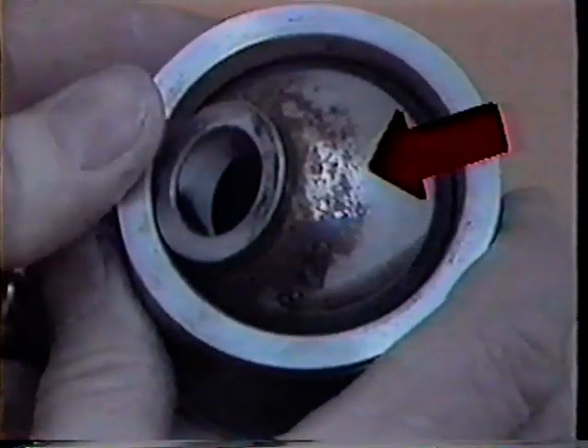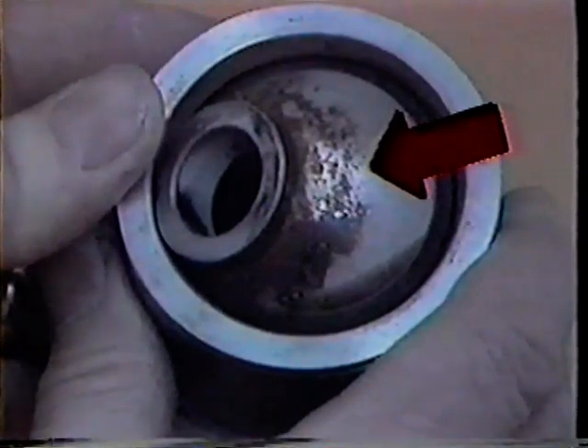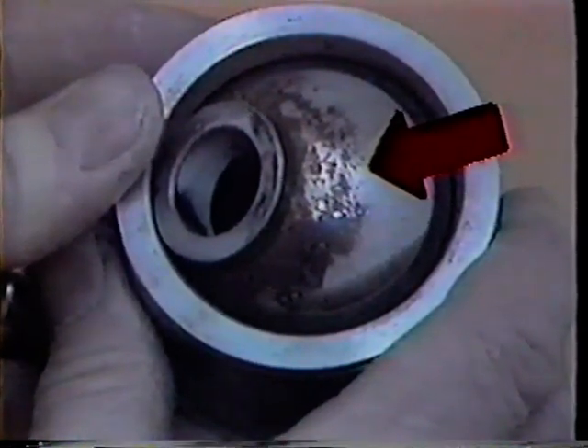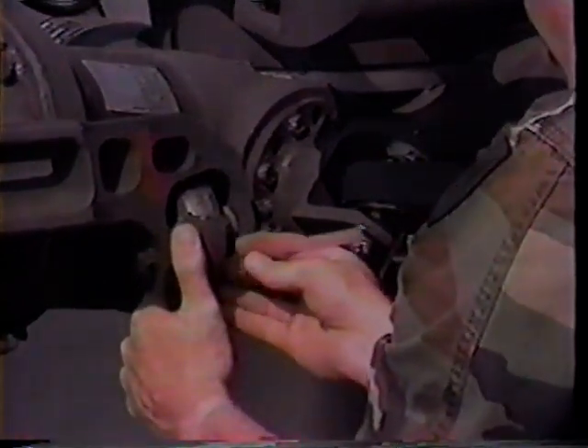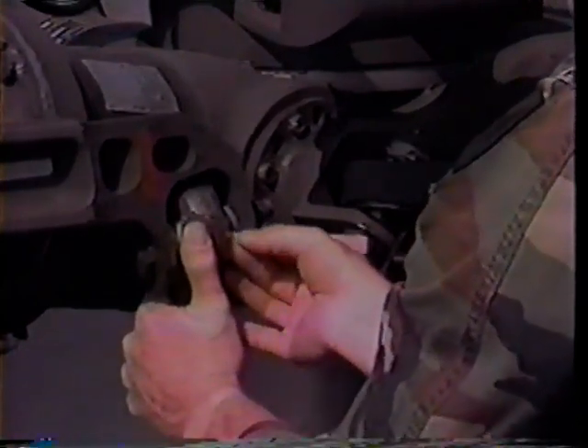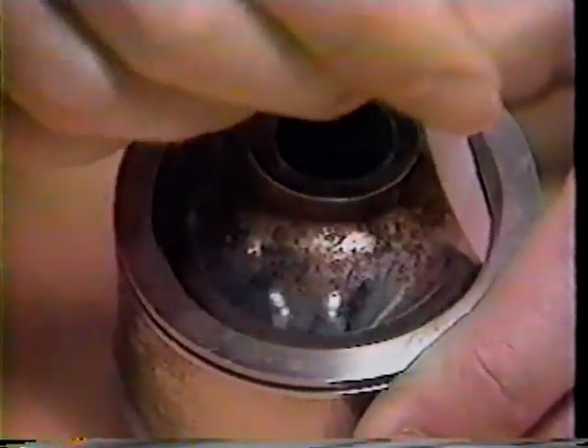Corrosion may develop closer to the neck portion of the ball, the area not in contact with the Teflon. The corrosion here does not get wiped away by the normal movements of the bearing. During inspection, clean off the ball with a scouring pad. Then check the ball for pits and count the number found. Compare your findings with the accept-reject criteria found in the manual. At the 30-hour special inspection, use the plastic feeler gauge to measure bearing wear. Check this against acceptable wear criteria found in the manual. These assemblies must be replaced when the gap between the liner and the ball exceeds the allowable clearance.